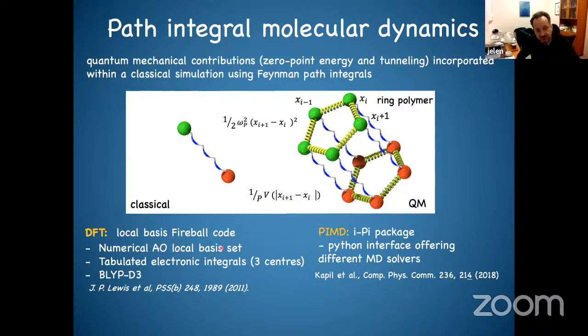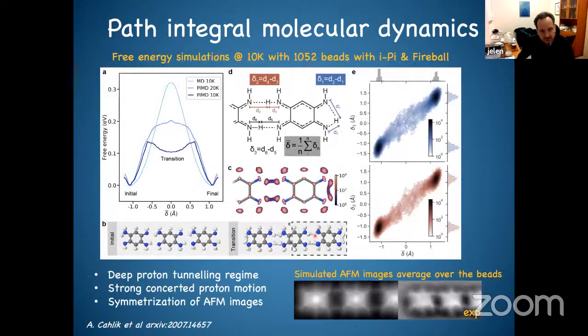This is our home-built code, which is then connected with this path integral molecular dynamics, which is extra code. It's an interface which is running and calling this DFT. So we did these calculations here, and this is the result. These are the barrier when we move a proton from one side to the other. So I take the proton from here to here, and this is the barrier. This is a classical barrier at 10 Kelvin. It's about 300 millielectronvolts. Now I can do the same with this path integral molecular dynamics.